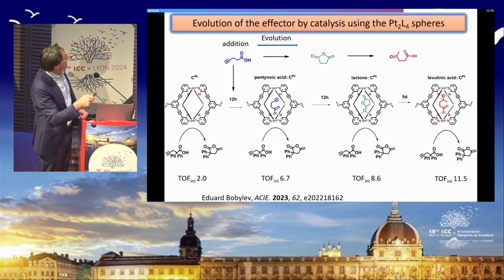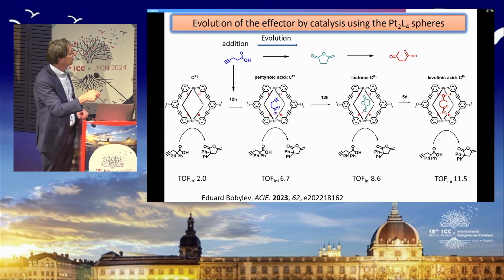So then we did an evolutionary experiment where we looked at the evolution of effectors that change reactivity. So we started with this catalyst that doesn't have any effector at all, and then we have a turnover frequency of 2 per hour, cyclization. Then we add this substrate that is bound. It's known to be a cofactor to control this reaction, so the reaction goes up, but it is also converted itself. So over time, this forms this cyclic compound, and this cyclic compound is completely formed after 12 hours, is again an effector. So we added more of the substrate, and now it's converted with even higher reactivity.